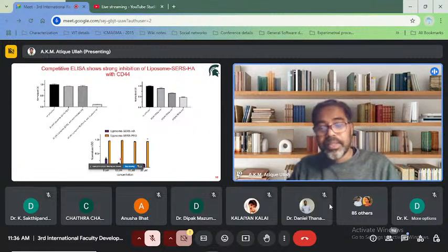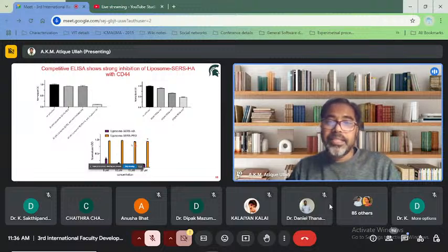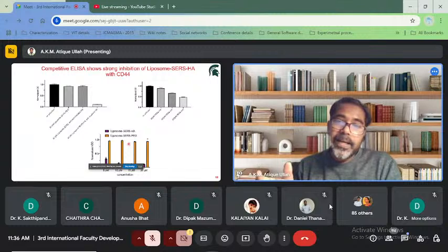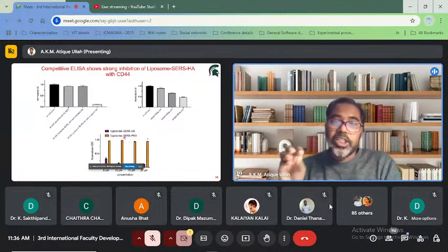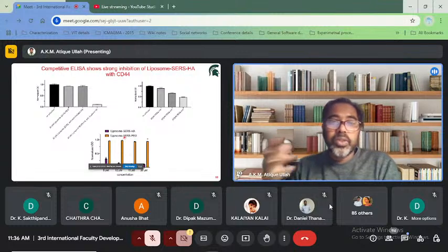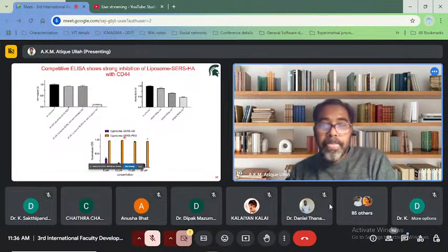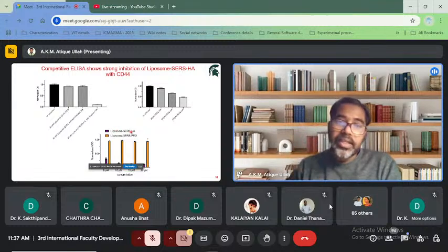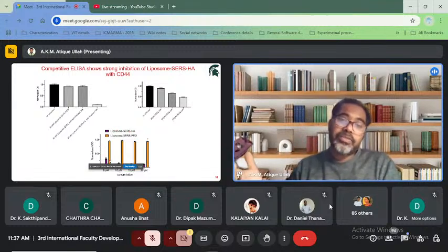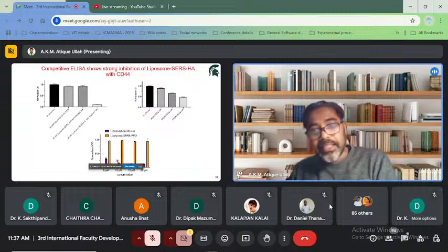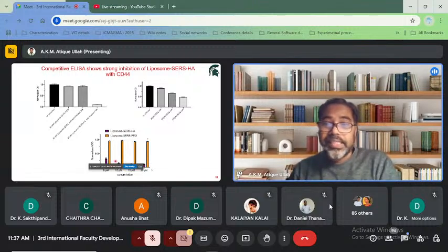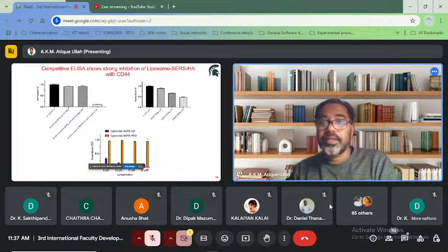this is just the comparison. You can see this is liposome SERS HA, this is the PEG. So from the optical density measurements, you can easily see that the PEG one, which is non-targeting, cannot show any affinity towards the CD44 protein, but the liposomal SERS HA can bind with the CD44. And also the binding affinity is increased with the increase in the concentration of the SERS nanoparticles.